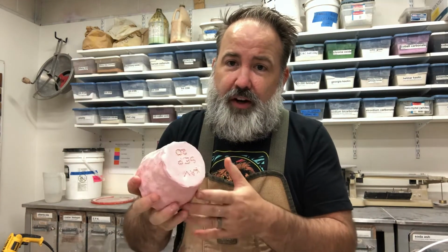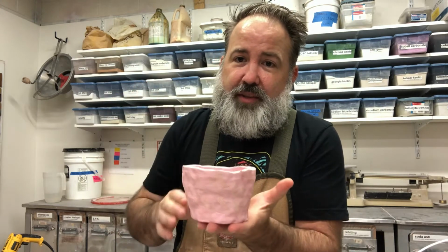The other thing that can be on the bottom is the colored slip that we used during the process of making your object. Remember, the slip has to go on when it's wet or leather hard. You cannot use the slip on bisque fired objects. So once it's bisque like this, it's too late for the slip. If you try to put it on, it'll just chip off. But you can see this object here, this person applied the slip to the bottom of the work, and this person could fire this on the bottom and that slip will not stick, okay?